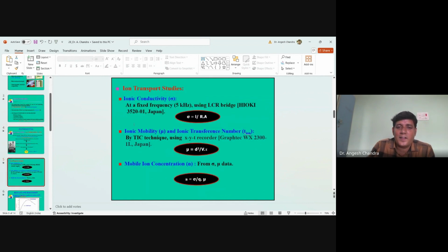Now in the ion transport studies, we have calculated the ionic conductivity. Sigma is equal to L upon RA, where L is the thickness of the sample, R is the bulk resistance obtained from the LCR bridge, and A is the cross-section area. Ionic mobility and mobile ion concentration we have also calculated by the transient ionic current technique using the XYT recorder. With the help of this formula, mu is equal to D square upon V tau, where D is the thickness of the film, V is the applied potential, and tau is the time of flight obtained from the XYT recorder. And we have also calculated the mobile ion concentration using this formula: n is equal to sigma upon q mu.